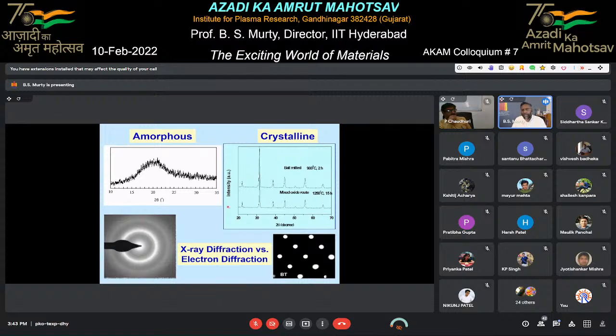But the moment a material is amorphous, like a glass, for example, we all know these window glasses. If you put a window glass in an XRD machine, you get a broad peak like this. This tells you that there is a random scattering happening, but because there are no clear crystallographic atomic planes, you get a broad peak.